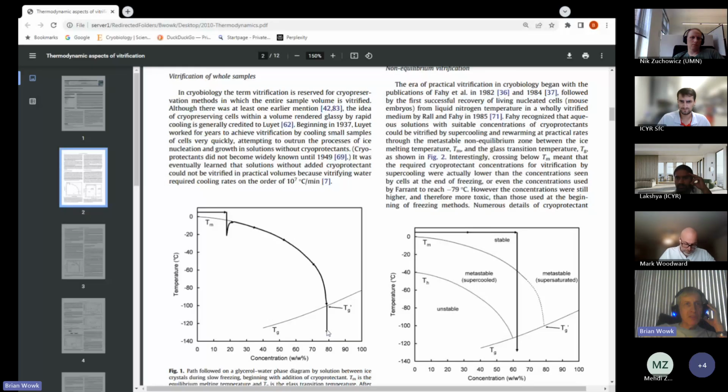So that's standard freezing. But there's something else you can do, as I'm sure you all know, and that is if we take this phase diagram and we add on another curve, the homogeneous nucleation temperature, we can look at some different phenomenology here. So the homogeneous nucleation temperature, Th, is the temperature below which the solution cannot supercool.